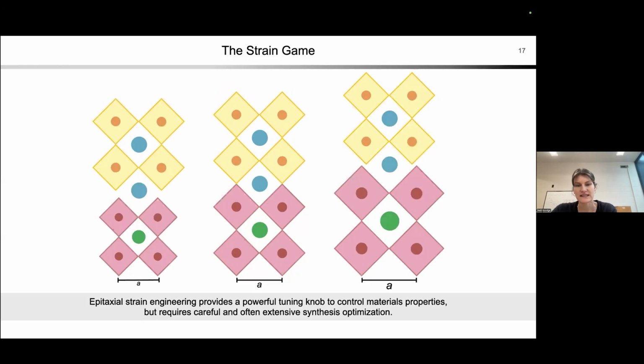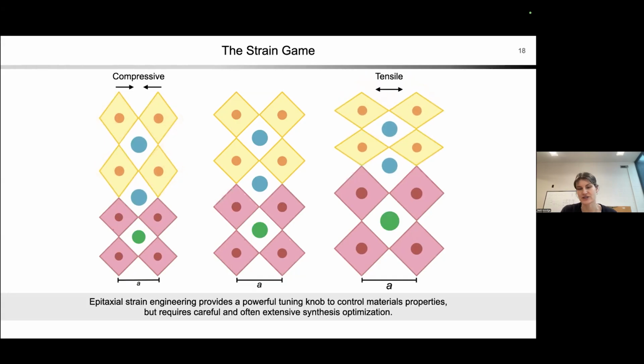Now, the challenge is that if you want to take that top material, in this case the yellow one, and for some reason put it on top of a material with either a much smaller or a much larger lattice constant, like you see on the left and the right, then you can imagine that as you put the yellow material down, something has to happen. It has to accommodate its structure because it still wants to maintain all of these atomic bonds. And so what can happen, if you're very careful, is that you can stabilize different kinds of what we call strain. You can see that the material distorts itself to fit onto that bottom layer.